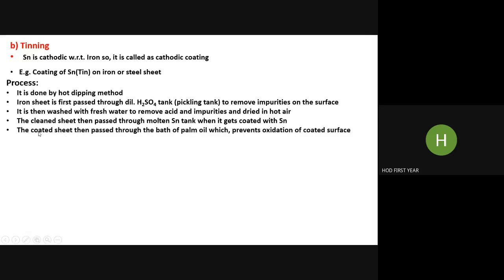Okay, and now once it is coated, it is passed through an oil bath to avoid oxidation. It is passed through a bath of palm oil, which prevents oxidation of the coated surface. Okay, and then it is passed between hot rollers to remove excess tin.